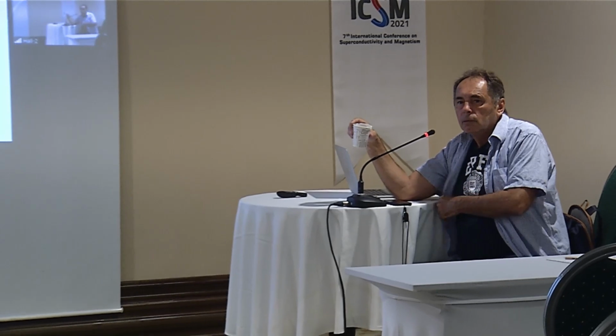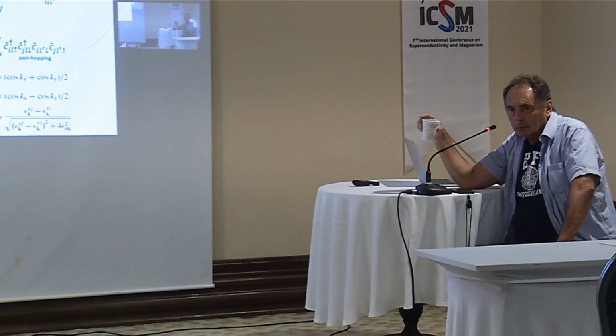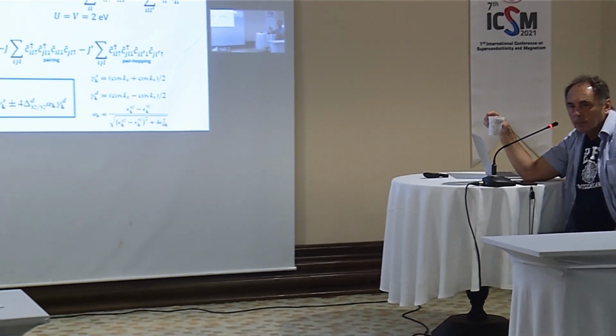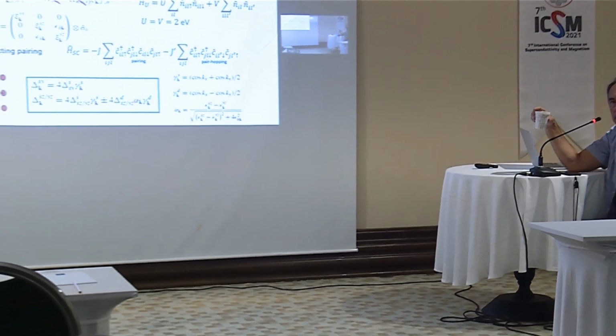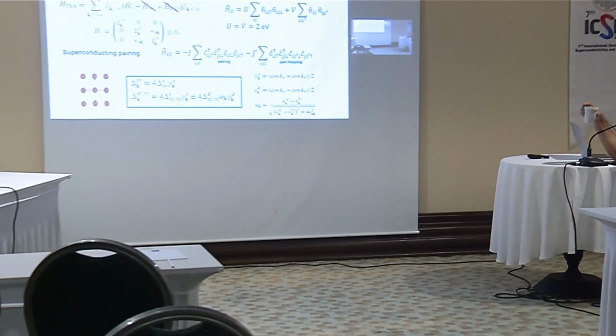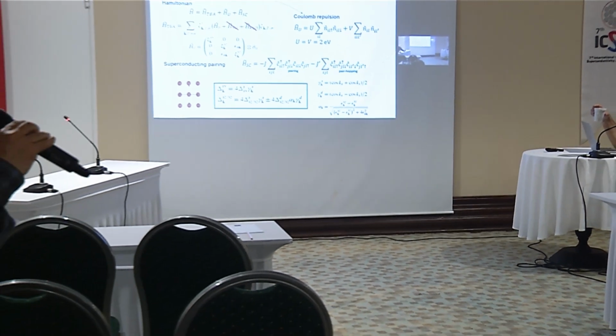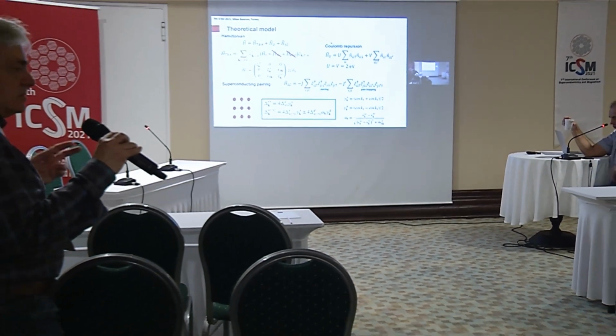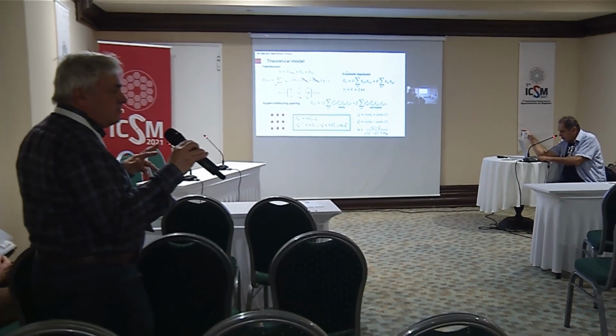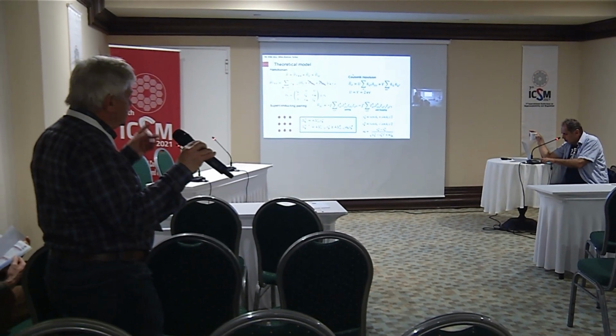Yeah, the main mechanism which we use is just the electron-phonon interaction. Okay. Together with Coulomb, without any assumption of the strengths. So we account for the retarded character of the interaction and work beyond the adiabatic approximation for the effective interaction. But what was simplified, of course, we did not take into account this extension of the symmetry.